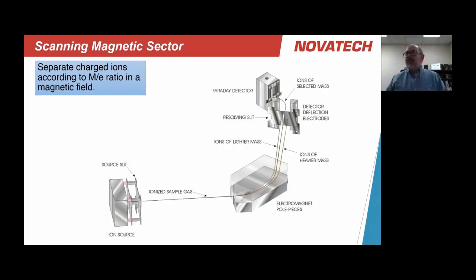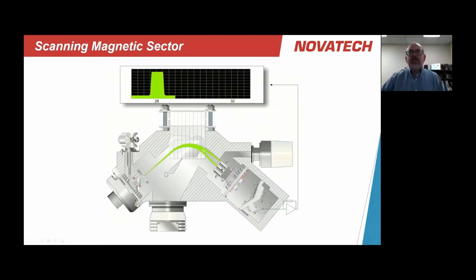In a scanning magnetic sector, same concept, but we're using an electromagnet now. So as our ions are fired out of our ion source, our positively charged ions travel down towards this electromagnet, and the field strength that we apply to this electromagnet will divert the beam path. And by varying this field strength, we change the arc of the field path. So different ions will hit our detector at the end. And there's an illustration here. As we change the field strength, we have different mass to charge ratios hitting the detector. I think this is a good representation. It makes it clear how it works.